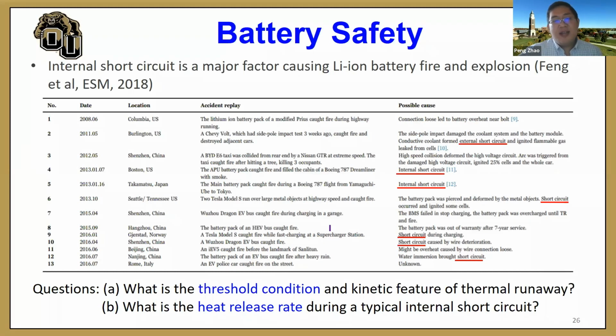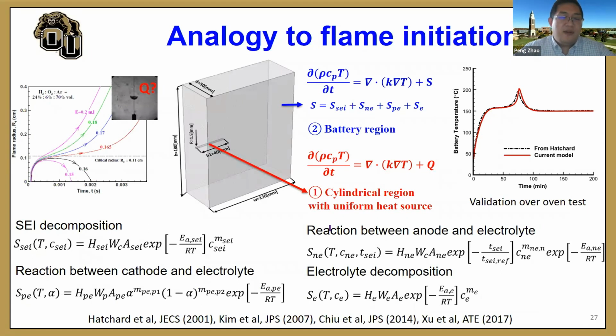By drawing an analogy to the hotspot ignition of flames, we can build a model to describe the thermal runaway of lithium-ion batteries. Compared with combustion chemical kinetics, you can see that the chemical reactions in battery thermal runaway are still in the infant stage, where we use very global heat source terms to describe some semi-global reactions, like in 4 reactions: SEI decomposition, reactions between the anode and the electrolyte, reactions between the cathode and electrolyte, and the electrolyte decomposition reactions. These reactions include many parameters that are to be determined from TGA, DSC, or ARC experiments.